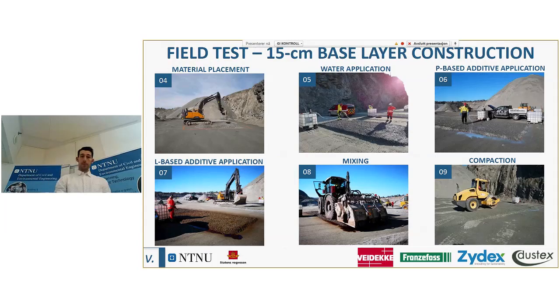So here we have the other pictures, actually, which let us better understand the main steps of the construction. First we built our 15 centimeter layer, so of course we placed the material. Afterwards, we applied the water on all three areas. We applied the polymer-based additive on one area, and of course we applied the lignin-based additive on the third area. We mixed all this water, additive, and rocks together properly, thanks to the action of a proper mixing tractor, and afterwards, of course, we proceeded with the compaction.